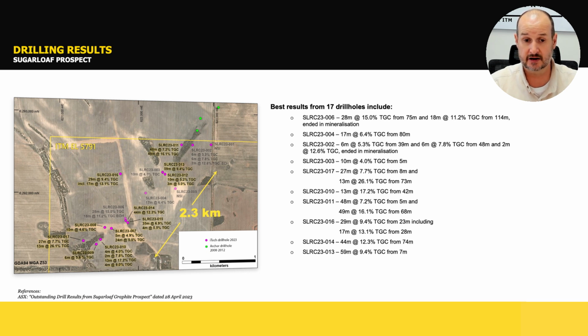And then there was a really high grade interval in hole number 17, where the top half was a bit lower grade, 27 metres at 7.7 from just 8 metres, so just below surface. But then a bit deeper, we had 13 metres at 26% total graphitic carbon from about 73 metres. So you can see there's significant graphite mineralisation over that whole 2.3 kilometres.